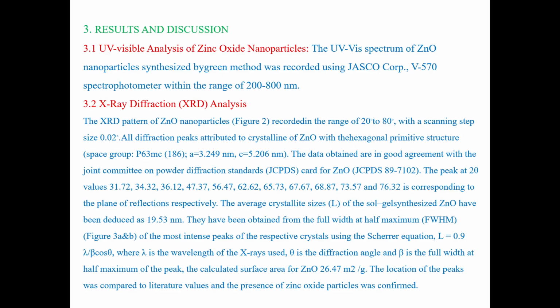The XRD pattern of zinc oxide nanoparticles, that is the below figure, recorded in the range of 20 degree to 80 degree with a scanning step size 0.02 degree. All diffraction peaks attributed to crystalline zinc oxide with the hexagonal primitive structure. Space group P63mc 186, a is equal to 3.249 nanometer and c is equal to 5.206 nanometer. The data obtained are in good agreement with the Joint Committee on Powder Diffraction Standards, that is the JCPDS card for zinc oxide nanoparticles.